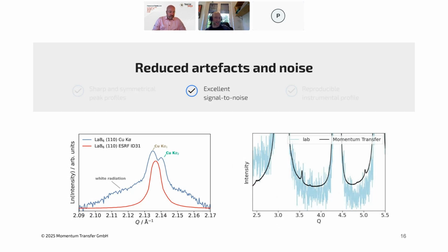In terms of noise, also the detection limits, so the ability to resolve phases at much lower weight percentages is possible, because essentially we can reduce most of the noise from the statistics of the measurement itself, and rather the remaining noise in our measurement comes mostly from the detector itself. So for typical lab systems with multi-phase mixtures, oftentimes you can get detection limits down to 1 weight percent, maybe 0.1 weight percent if you have a really, really good system and really, really long measurements. For us, in just a few seconds, we can get detection limits oftentimes down to sub 0.1 weight percent, in some cases down to 0.01 weight percent.